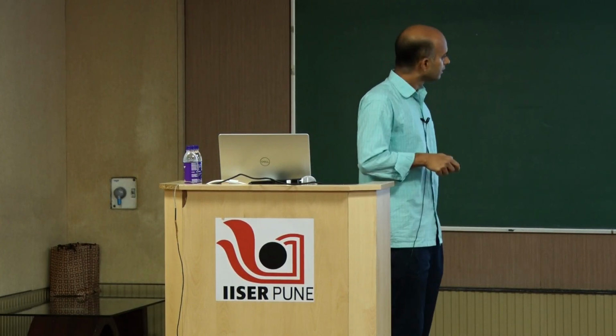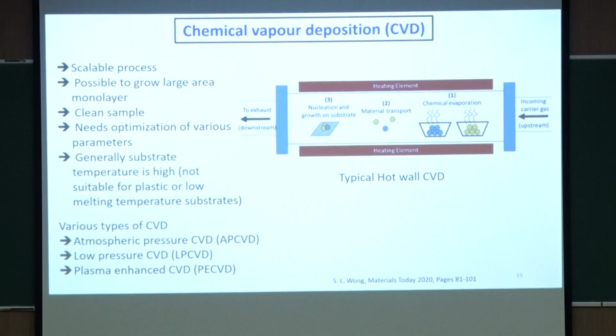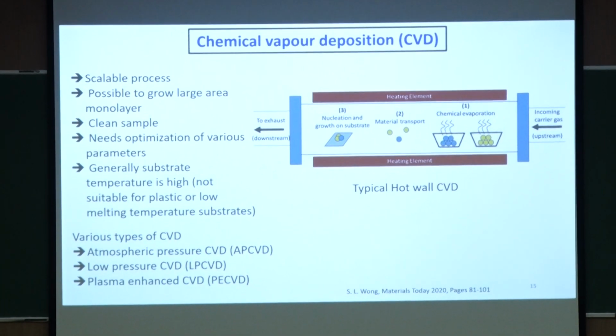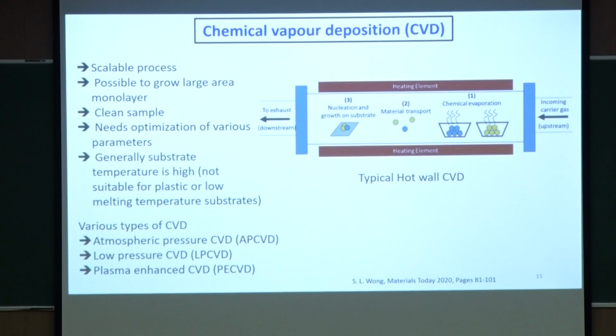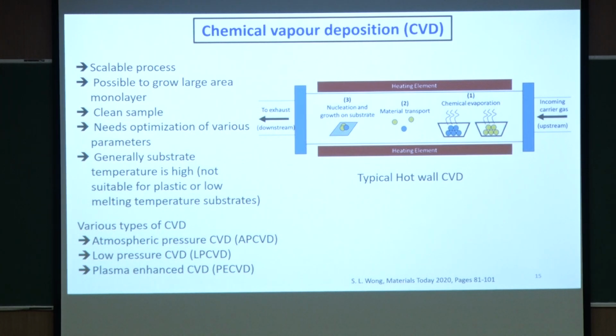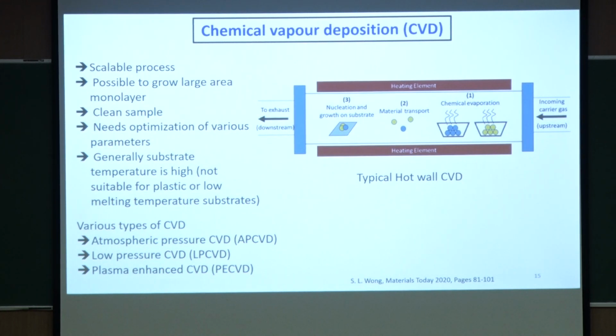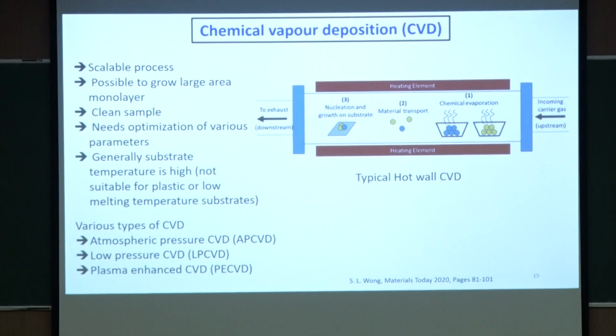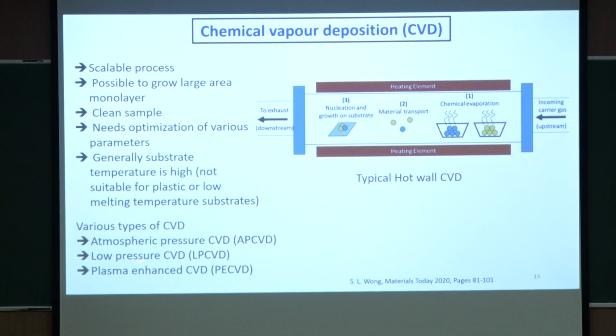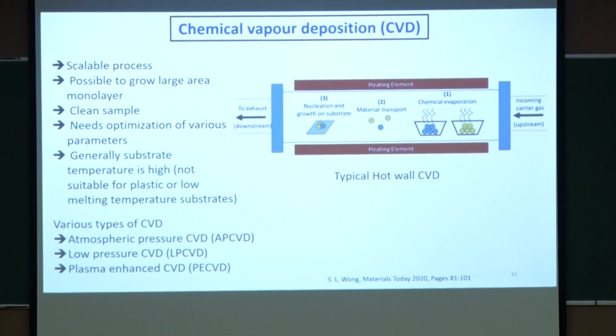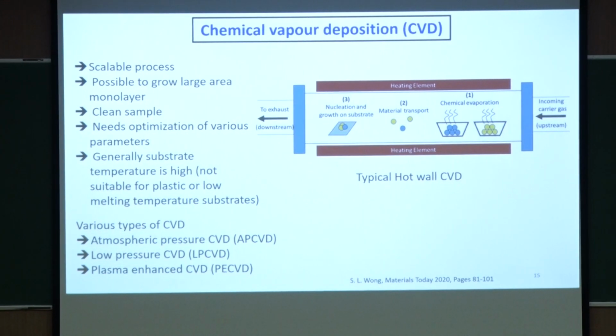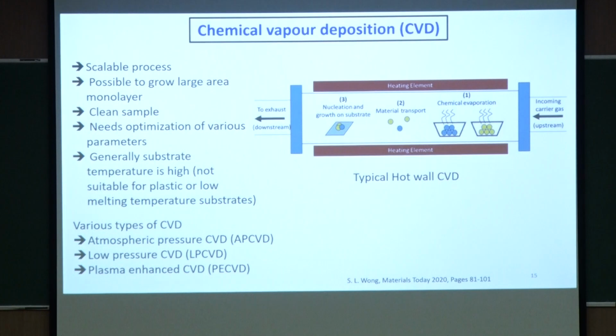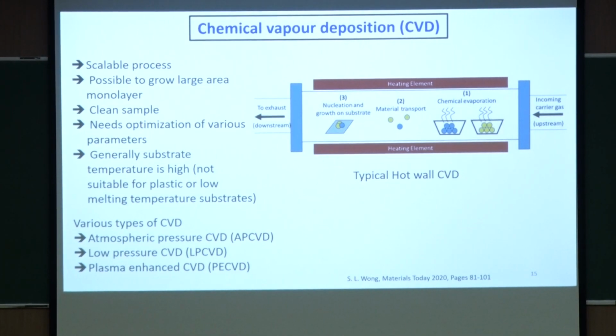There is also cold wall chemical vapor deposition, where the heater is not outside. Wherever your precursors are, the heater will just sit over there, so your wall remains cold. Now, chemical vapor deposition, depending on the conditions, can be atmospheric CVD, which works at atmospheric pressure, so you do not need vacuum, or you can convert it into low pressure chemical vapor deposition for certain materials. That is also very helpful. You get cleaner samples, or sometimes it is easier to get a continuous monolayer sample using low pressure CVD. Or there are other sophisticated variants like plasma enhanced chemical vapor deposition, especially for depositing oxide and SiNx, mainly silicon nitride.